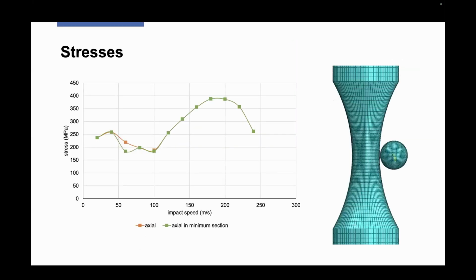What is strange is what happens to the axial stresses. Here we can see the trend for axial stresses in the specimen wall and in the minimum cross section, where the highest total stresses are expected to occur during the fatigue loading. So you can see that we have an increasing trend for very small velocity, then a decreasing trend, then again it increases and decreases. It's a strange trend, and maybe there are a lot of motivations to explain it.